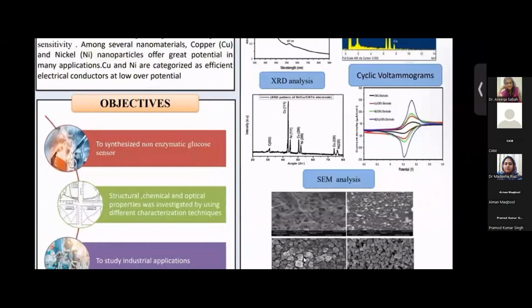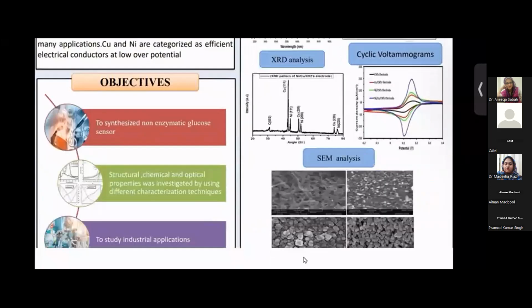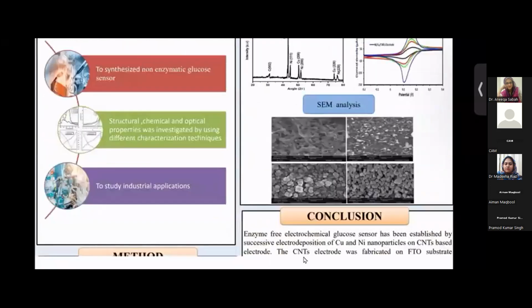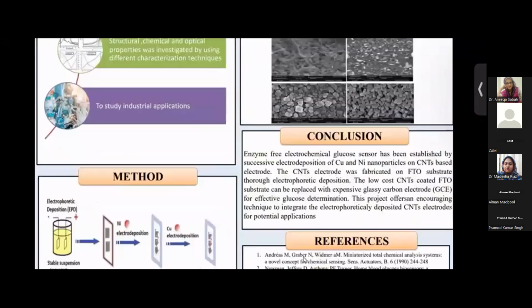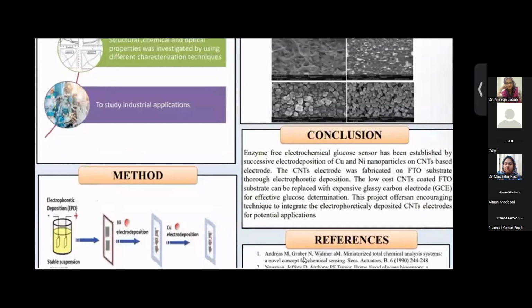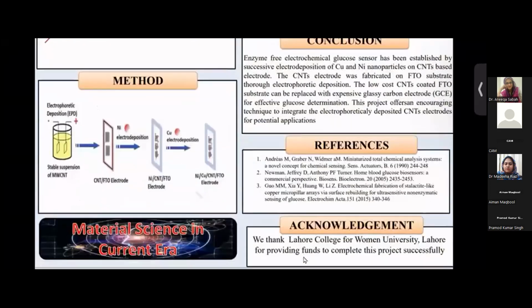The small particles of diameter 20 nanometer correspond to nickel, and the large particles of diameter 70 nanometer correspond to copper. Conclusion: an enzyme-free electrochemical glucose sensor has been established by electrodeposition of copper and nickel nanoparticles on carbon nanotubes-based electrodes, and these are the following references and acknowledgement.